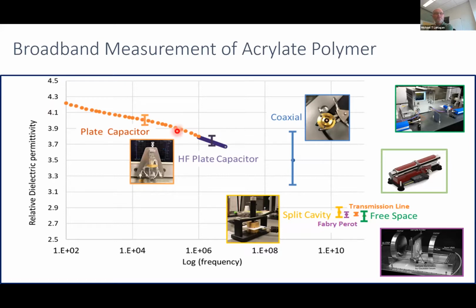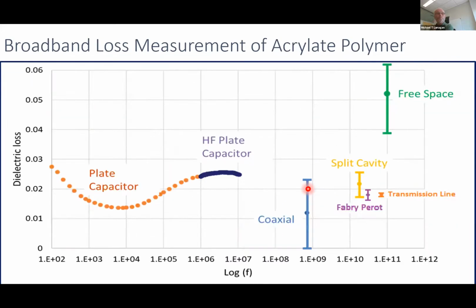So this is the permittivity as a function of frequency. What we can also do is measure the loss. Remember that we need to measure both the loss and the permittivity to get a fundamental idea of what's going on with our materials. And again, as we go from 100 hertz all the way up to 100 gigahertz, we can see general things occurring.